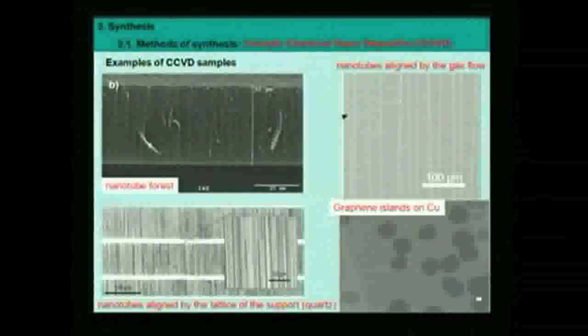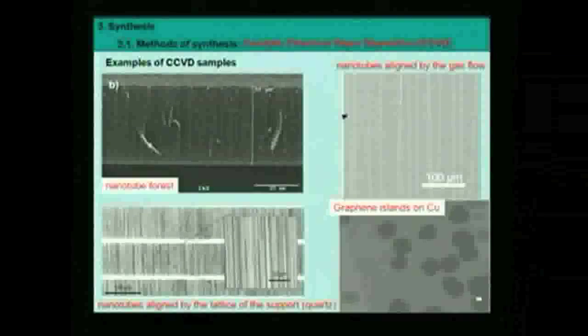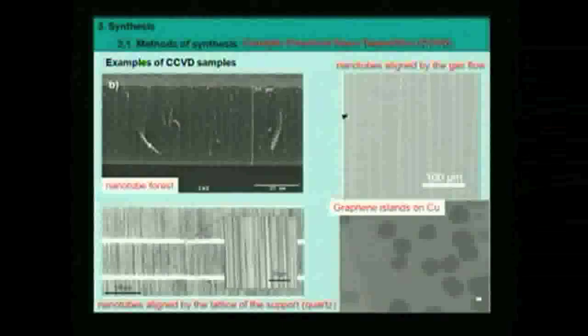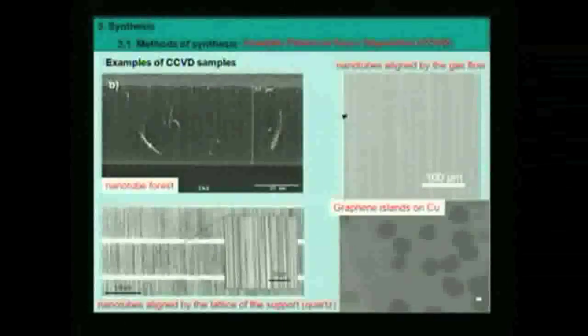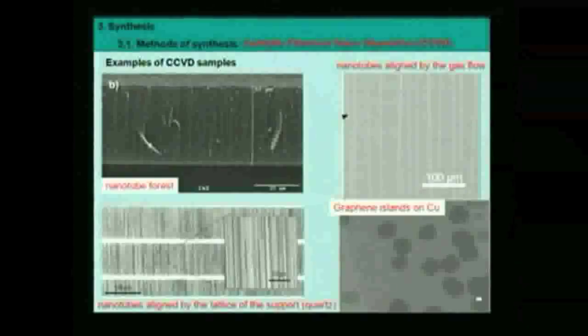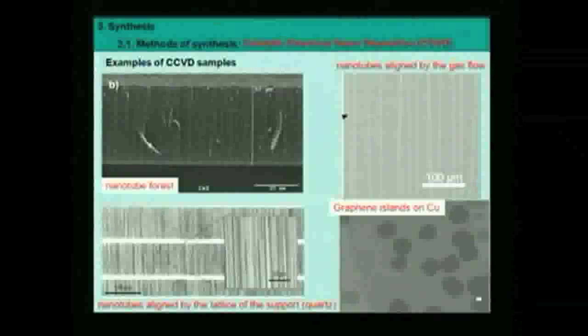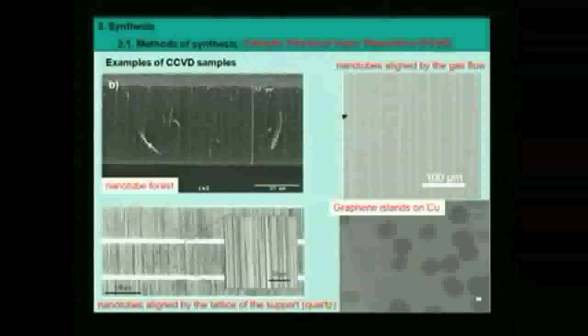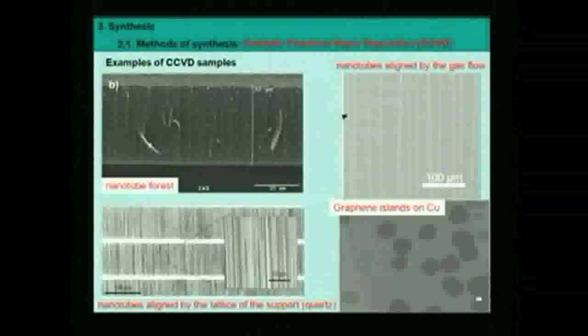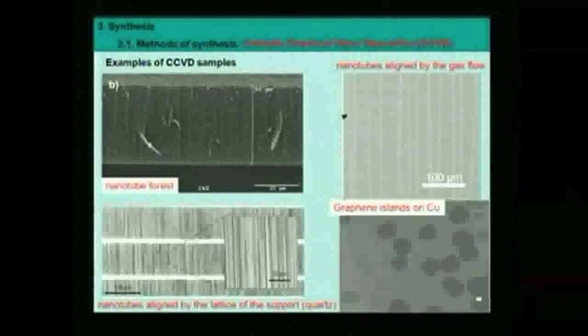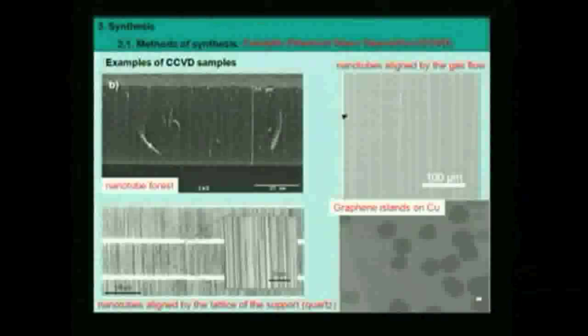Okay, examples now of what you can obtain using CCVD. For instance, you can obtain a forest of nanotubes, a very thick and dense forest of aligned nanotubes. What do you see on the left top picture? This is an SEM picture. At the top here, this is the support. It's usually silicon oxide. And perpendicular to this support, nanotubes have grown like a forest, like a carpet, like grass. It can be very thick, as you can see here, 36 microns, but much thicker forests have already been grown, having several millimeters of height.